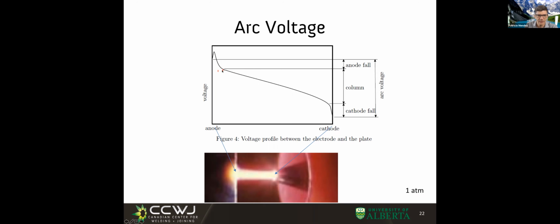This thickness here that I have here is of the order of 100 microns. This thickness here is of the order of 100 microns. But 100 microns is 0.1 millimeter. But the arc can be 10 millimeters, right? It can be 100 times that length. This part is proportional. But this part that is near the electrodes has these very big and very fast voltage drops, right? And you get to see that I made it go a little bit up before it comes down. I'm going to discuss this in a minute.